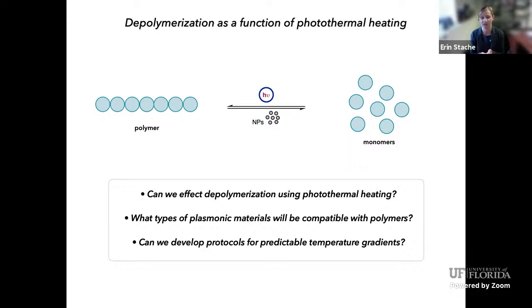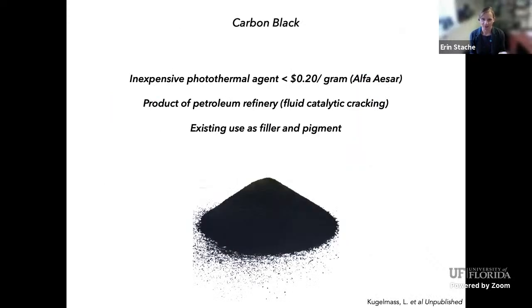So what photothermal agent are we going to use? I've already said that gold is maybe not the most practical for doing large-scale recycling of commodity polymers. And so we turn to something that's already used in polymer chemistry pretty frequently, and that's carbon black. This is a very inexpensive photothermal agent. We spent 20 cents a gram from Alfa, but it's much cheaper than that. It's a product of petroleum refinery, and it's already used in polymer chemistry as a filler, as a pigment, as a UV stabilizer. It's a broadband absorber, so that means we should be able to hit it with multiple wavelengths of light and perhaps generate these temporal heat gradients to depolymerize cyclic polyphthalaldehyde.